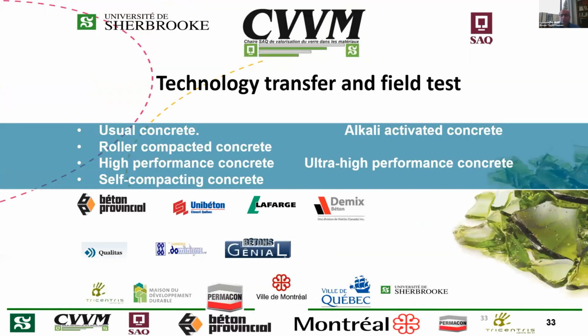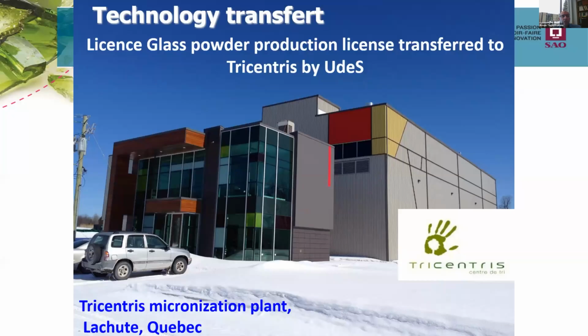The technology transfer and the field test of this material: we did a huge program of testing the glass pozzolan in different places. So, as I said, we worked with usual concrete, roller compacted, high performance, self-compacting, alkali activated, ultra high performance, and all these companies you can see here used this material at a given time.